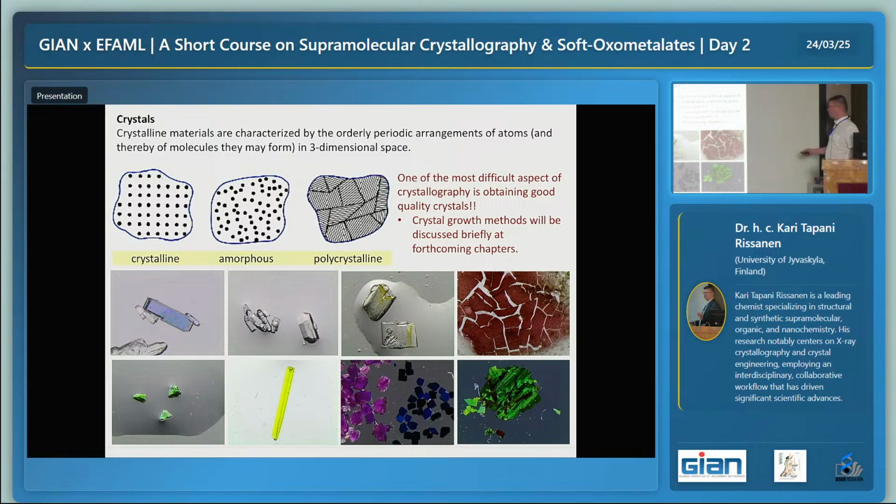Sometimes when you look, there are all microscopic images, and later on you will learn why we need the microscope for this. So you might see two completely different colors, and you can see it's nicely separated: the pink colors are on this side, and the purple-blue colors are in here. This is actually the same crystal, but the orientation of the crystal is different. So you can consider these pink ones are like this, and then the blue ones are like that. And then this is anisotropic in that sense. The color, the wavelength, is different: you get a different wavelength going through the crystal.